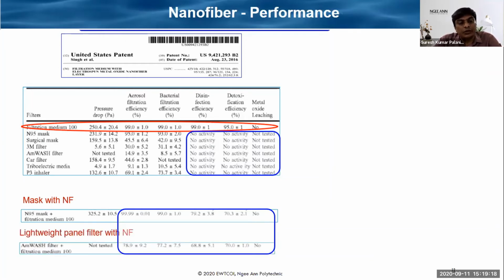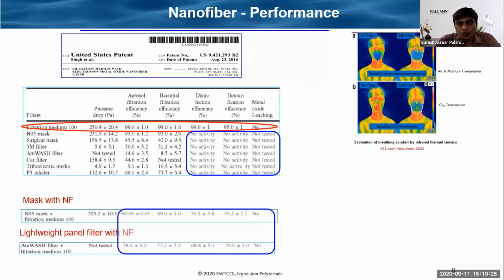We also tested the nanofiber with lightweight panel filters. The efficiency for disinfection and detoxification is around 70%. We also found recent literature on the breathability of nanofiber filters and melt-blown filters, and it clearly shows nanofiber has a better advantage over melt-blown filters. The air and moisture transmittance and the CO2 transmittance are more comfortable for nanofiber than melt-blown filters.